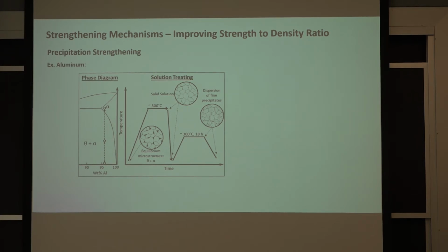So all those atoms that were in these little second phases, through the temperature, those second phases break apart and go into solution to form a solution strengthened alloy. In order to lock that in position, that material is then quenched. Now you've got a solid solution that's been quenched, and it is stronger than a pure material.